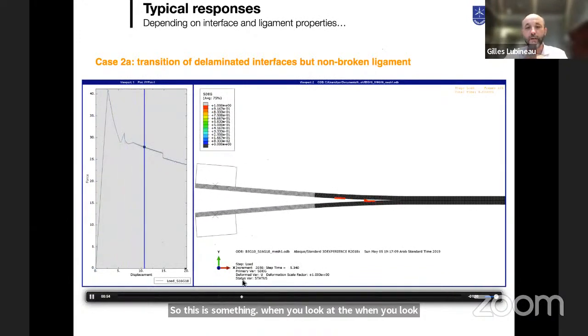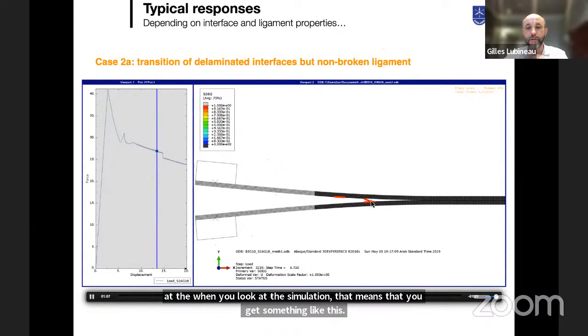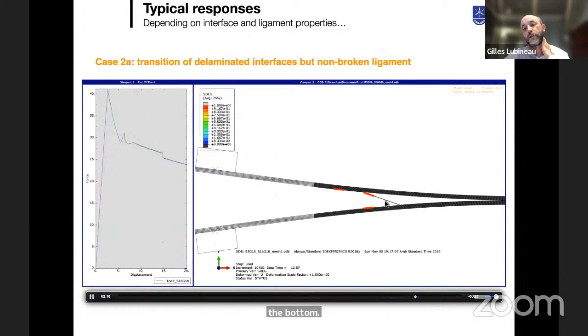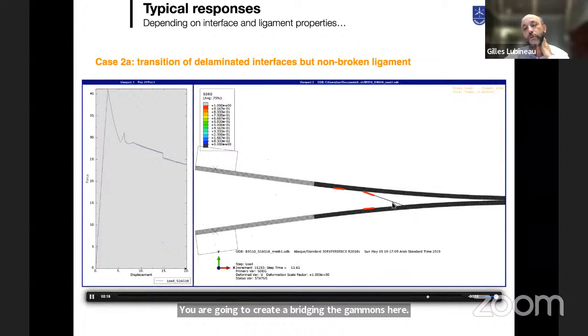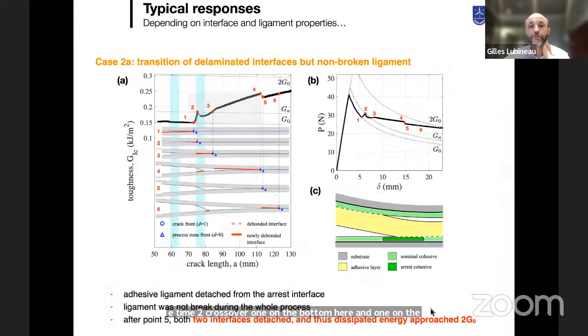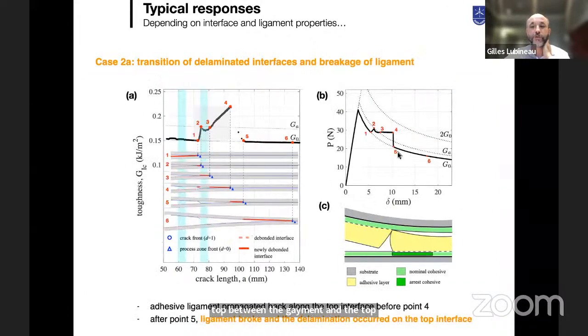That means when the crack is coming here on the bottom, there will be a bifurcation, and you are going to create a bridging ligament here with, in fact, 3 cracks that are propagating at the same time. 2 cracks, sorry, one on the bottom here and one on the top between the ligament and the top substrate. The third situation that can happen is the situation where you do exactly this. That means the cracks start to propagate on the bottom. It reaches the tough reinforcement, and you start to create this ligament, but the bottom is so tough that at the end, you cannot really propagate both cracks. You are going to break the ligament. So this is what you see here.